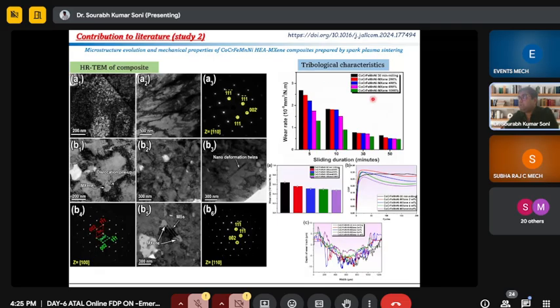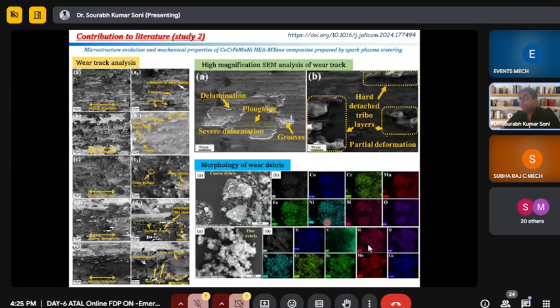This is the wear rate estimation and tribological characteristics we have done. So according to the sliding duration, what is the wear rate pattern is going on, we have analyzed. We have analyzed the coefficient of friction also, and wear depth of the wear track, so we can relate with the increasing of sliding duration or load, what is going on in the wear track of the specimen. Then to analyze the wear track surface, we have performed the SEM. Here we can observe what is going on in the wear track.